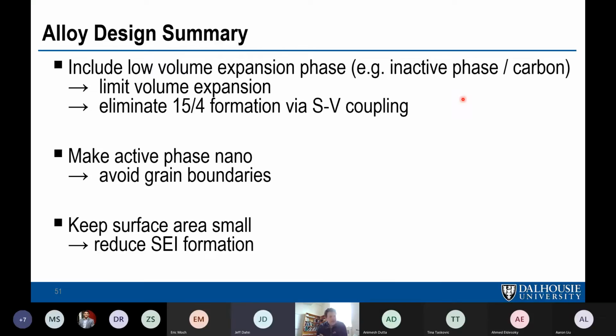So, this, I guess, goes for alloys. Let's see what it says here. If you want to make a good practical alloy, you should have a low volume expansion phase. Inactive phase could be a silicide or silicon oxide in the case of SiO, or lithium silicon oxide, or graphite or carbon, like was mentioned earlier. You want to limit the volume expansion by including this phase, and also you want to eliminate the formation of lithium-15 silicon 4 by the stress voltage coupling mechanism.